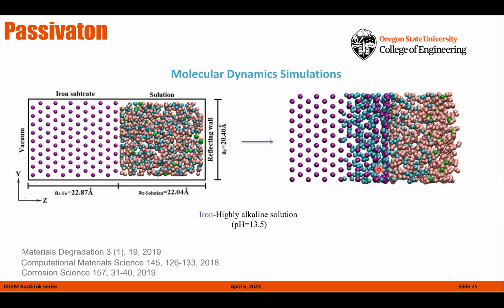So that epitaxial relationship that we have seen under TEM microscope actually is confirmed here. The film is not like a flaky film that forms on top of the steel metal. It is actually in a real connection with it, so it's organically connected, and organic, the word there is not in the literal sense.